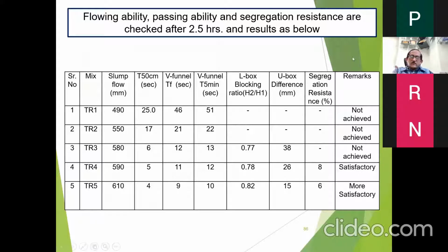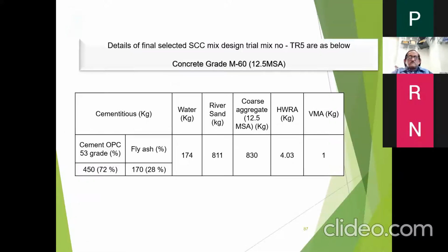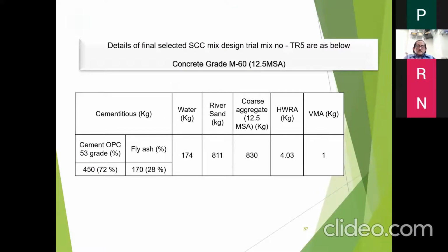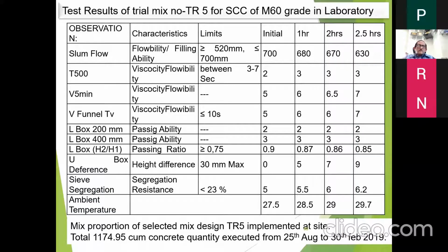And here it was not achieved, and hence this trial was rejected. Here we achieved it satisfactorily, but this was more satisfactory, so we went in for trial number 5. Fly ash was 28%, cement 72%. Coarse aggregate, river sand. And these are the values for the mix design TR5.